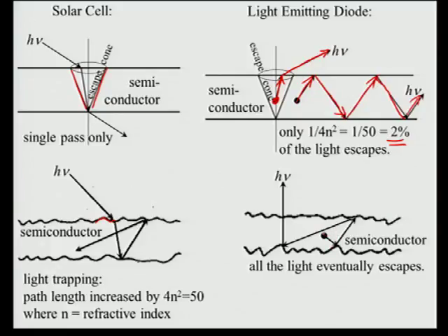And what it means is, yes, the light bounces around, but eventually it has at least a probability of escaping. And if you have very low parasitic losses, you can make a very efficient LED. LEDs now are way over 50% efficient, and the reason is they're breaking the plane parallel symmetry. They're introducing some geometrical shape that lets the light escape.